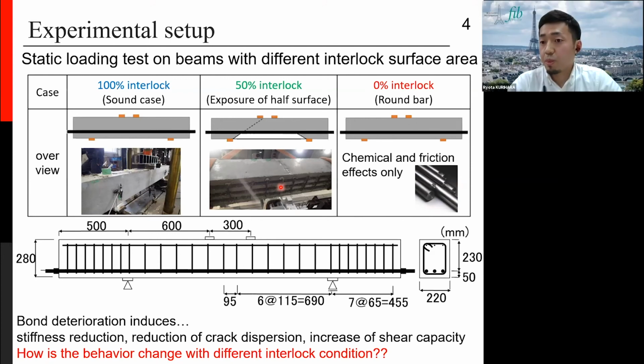Yes, in fact, my PhD thesis is larger, on the development of an analytical model of corroded rebar. This is the first step, and I picked up only one effect, the mechanical contact. And now I am conducting the next step, the effect of corrosion cracks, the longitudinal cracks. A new experiment, a rebar tensile test with concrete with corrosion cracks, is ongoing, but I don't have results now, so I'm sorry for not introducing it today.